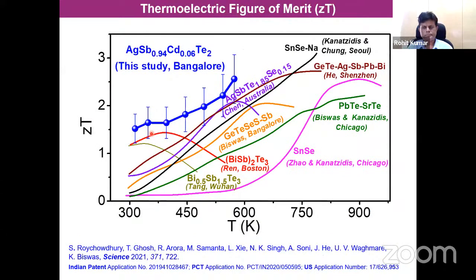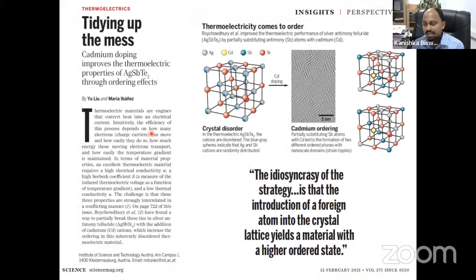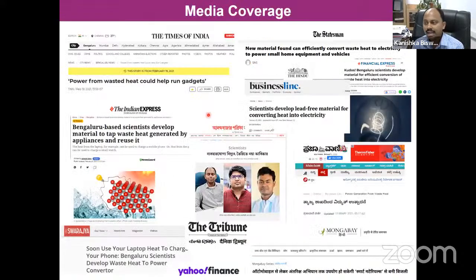So okay, based on our paper, in exactly the same year, another perspective came in Science by Maria's group from Austria. It was quite a sensation in thermoelectrics, because the thermoelectric field till now believed that disordering is good, because disordering scatters the phonon. But we said that disordering is no good. A little bit of ordering is good, where we can have delocalization of the electronic state, and if the ordering size comes fortunately in the order of a few nanometers, which can match the phonon mean free path, we can scatter the phonon also. That's what is written in the perspective by Maria, and it was highlighted in several media, from English to Kannada to Bengali, all kinds of media. It has highlighted this word.